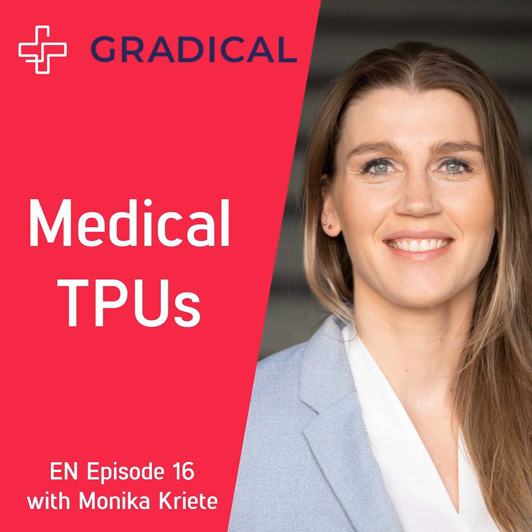Yeah, exactly. As mentioned before, there are some key principles in the synthesis of TPU which speak to a very low chance of having free isocyanates present in the final TPU, which comes down a lot to the kinetics of the reaction. As I said, we use a step growth polymerization, and in that, the speed at which a chain reacts with a free isocyanate is much quicker than with another chain, which leads to those free isocyanates being used up much more quickly, as the first reactive material of choice. I think this is the key thing which makes it very unlikely to have them present.